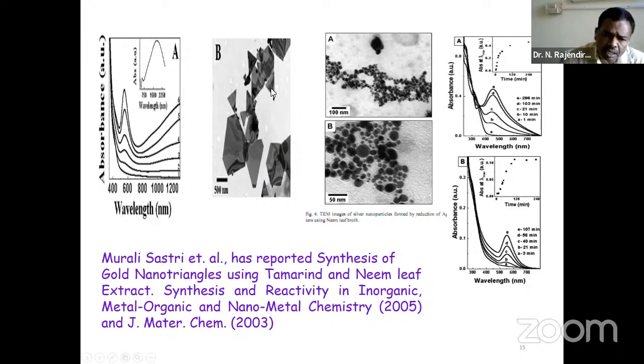You see that here, upon changing the amount of plant extract, we are able to prepare anisotropic metal nanoparticles. Here you see that these nanoparticles are either hexagonal, triangular, or pentagonal bipyramidal shapes. In the usual UV absorption spectrum, in addition to the formation of the SPR band around 500 to 600, another intense band appeared in the NIR region. That is characteristic of the existence of anisotropic nanoparticles.